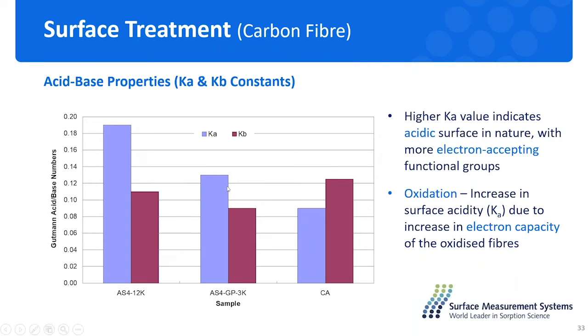And after sizing, which is the middle column here, the acidity of this carbon fiber becomes less compared to the sample without sizing, so it makes the sample more uniform or more stable for the application. So basically, the oxidizing of the surface will increase the surface acidity, which could be detected from the IGC technique for the Ka-Kb values.